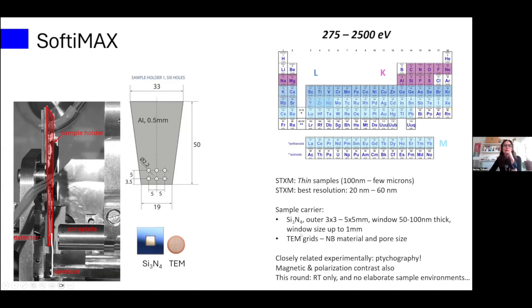The sample carrier, as said, silicon nitride, TEM grids, and the window thickness. Typically, what we tend to use is 50 to 100 nanometers thick. If you're not very used to working with these ones, I would go for the slightly thicker ones, simply because they are fragile and it's easy to break. And for the TEM grids, think about the material. So if you want to study the copper edge, maybe having copper TEM grids is not the best choice.